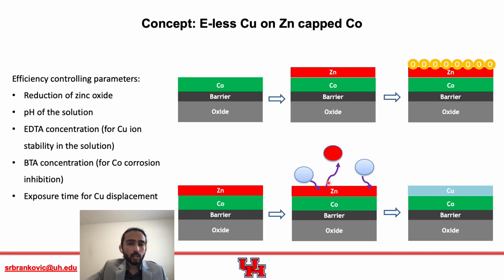Now, another variable which needs to be controlled here is the corrosion of the cobalt layer. Since copper is more noble than cobalt, if all of the zinc is consumed and we don't stop the process at this point, we would have compromised all the cobalt as well by galvanic displacement. So for that reason, we introduced BTA in the solution, which works as a cobalt corrosion inhibitor. And a layer of BTA protects the surface, and in the end we can have copper on top of the cobalt.